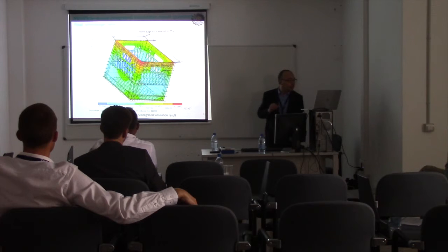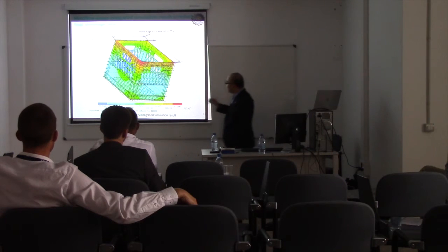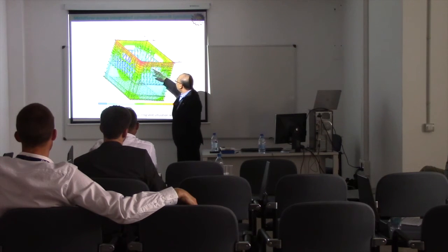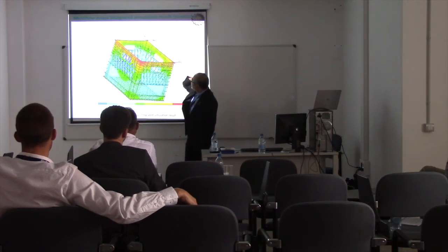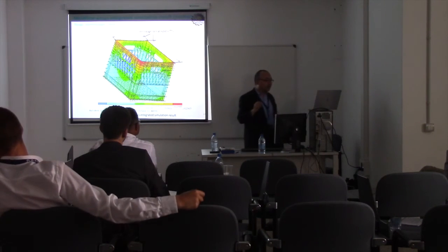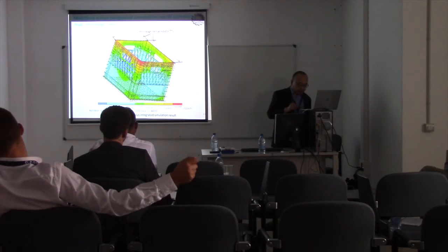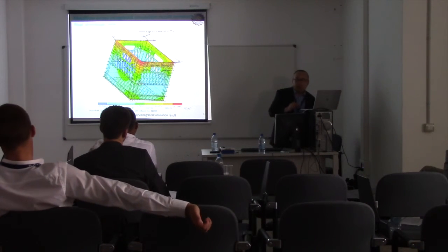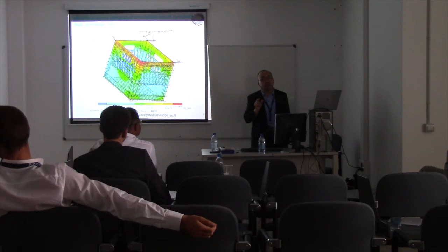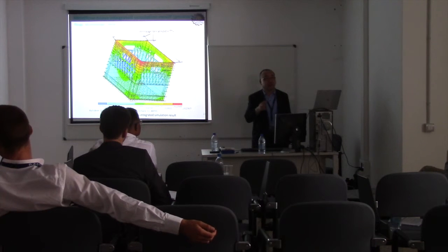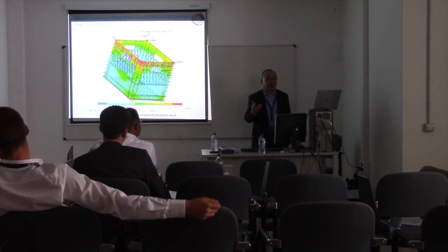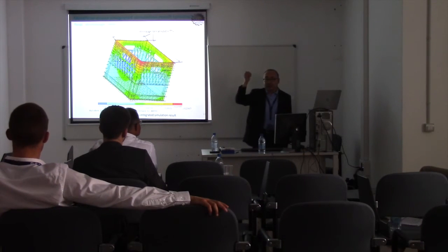And this is the integration after the mold flow pumps the data to ANSYS. You see the variation, and you see how much the difference is. We call this the shrinkage rate, and based on this, you see how things change, the dimension change. By the way, when we talk about the deformation, it's not 2-dimensional, it's 3-dimensional, because this is a 3D part. The rib strength will not be the same in different directions, in different locations. This is a spatial thing, right?